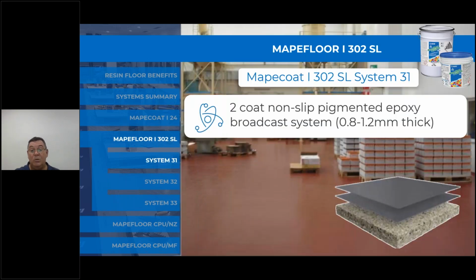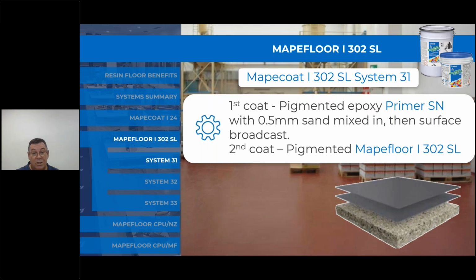The I-302 SL System 31 comprises 2 coats, non-slip pigmented epoxy broadcast between 0.8 and 1.2 millimeter thickness generally. The first coat is a pigmented epoxy primer SN, and it also has 0.5mm sand mixed in to add some volume to the mix, and then surface broadcast. The second coat is the Mapefloor I-302 in the same colour to complete the floor system, and that's a self-leveling 0.8 to 1.2 millimeter thick coating.